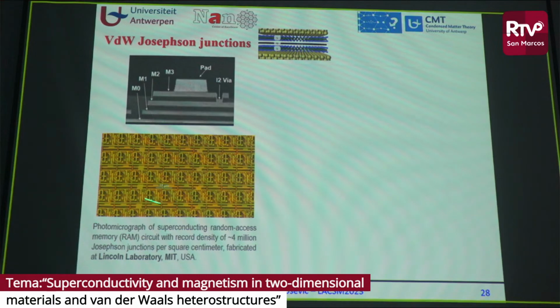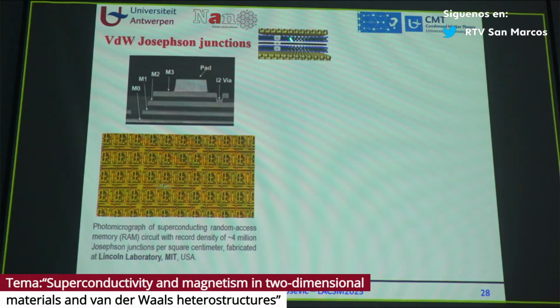And this is a photomicrograph of a random access memory circuit from Lincoln Lab at MIT, where they reported a record density of 4 million Josephson junctions per square centimeter. So manipulating these layers and controlling the coupling between them is crucial for this, and they identified these van der Waals Josephson junctions as the way to go forward.